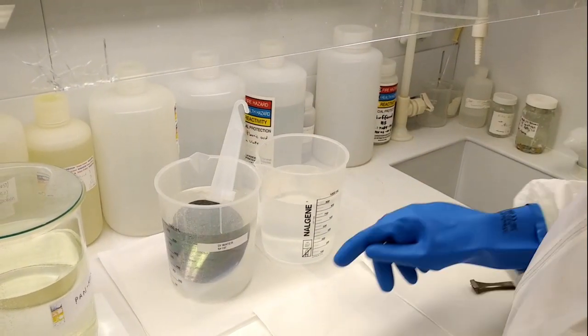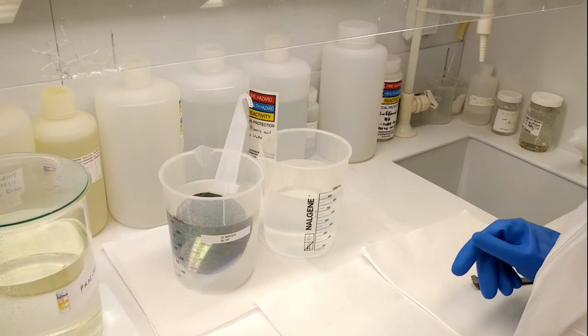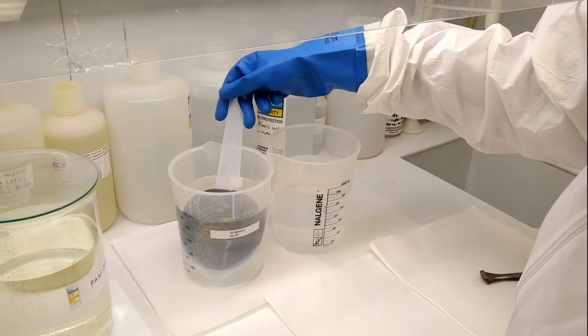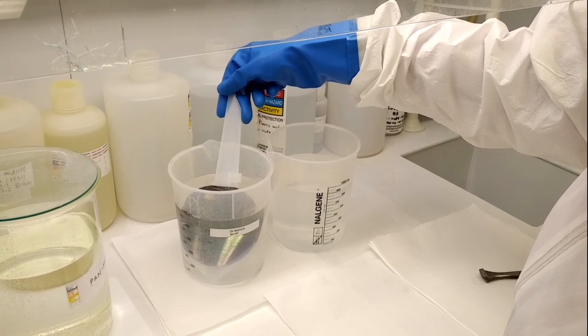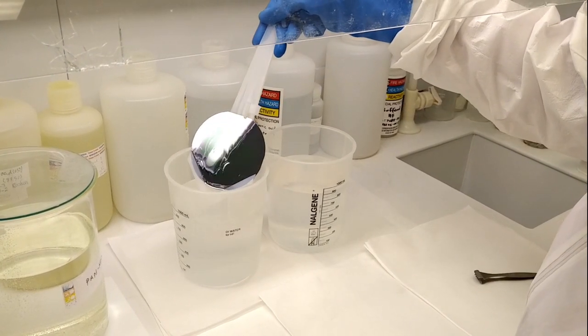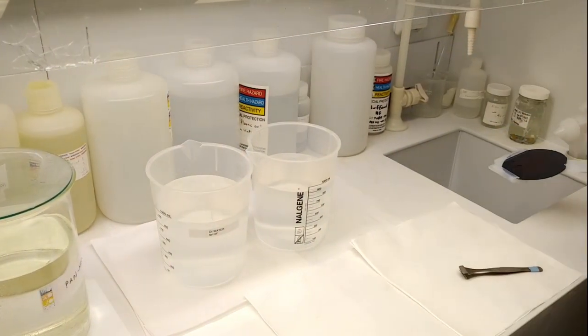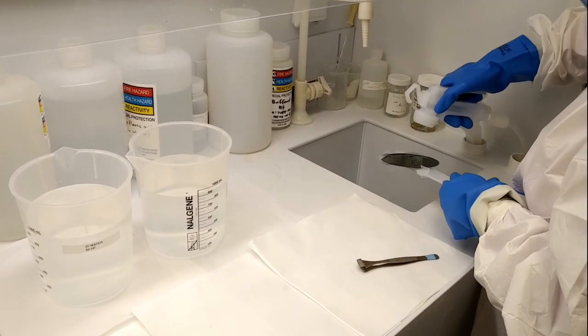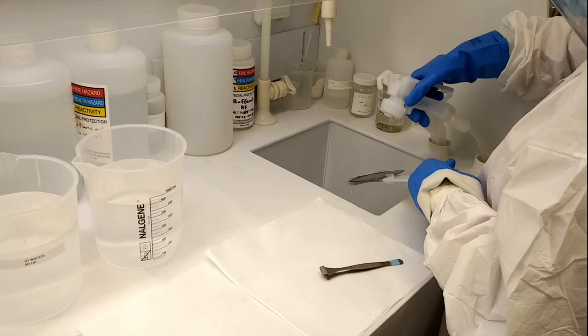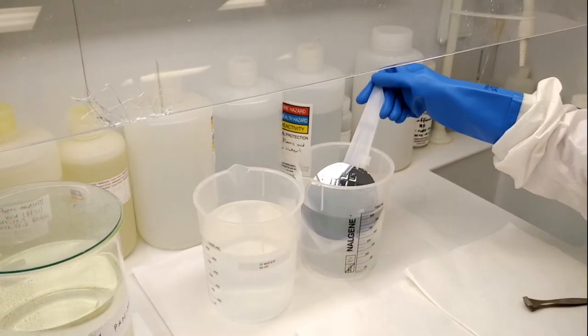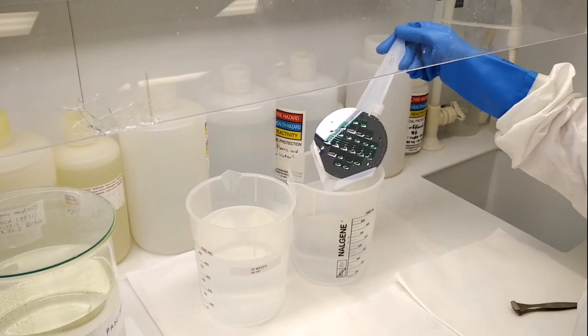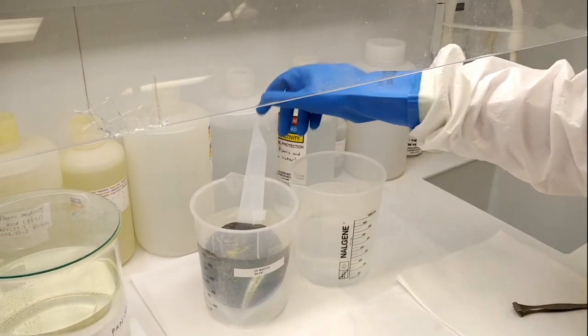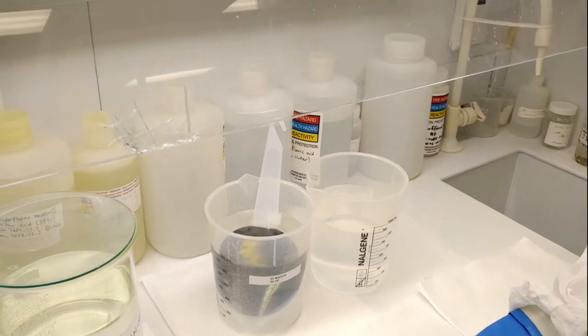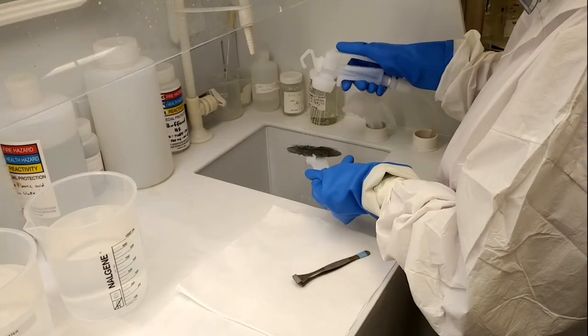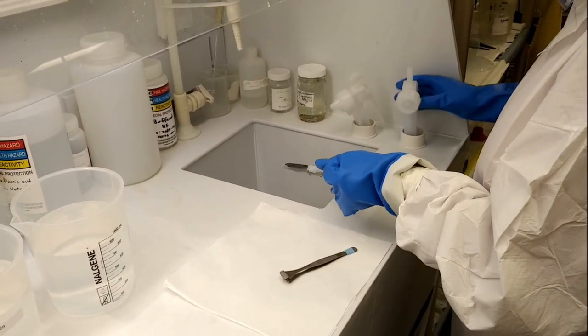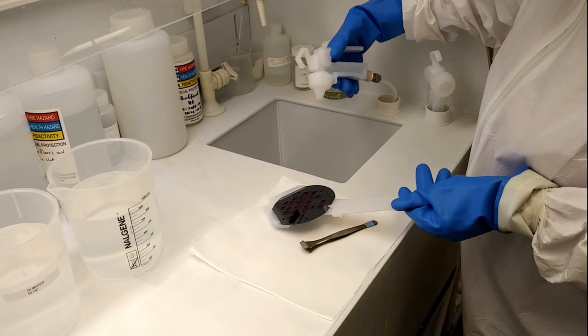The quality of the etch is checked by slowly removing the wafer from the buffered HF or water while checking for hydrophobic or hydrophilic behavior. The bare silicon that is exposed after the silicon oxide is removed is hydrophobic. When the liquid beads away completely from the exposed surface, this is a good indication the silicon oxide is completely removed. The wafer is then washed and dried and the resistance is checked.